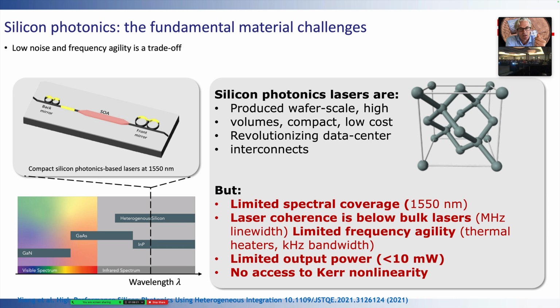material. And chief among them is the limited bandgap of 1 electron volt that prohibits making devices that operate in the visible. It has moreover limited power handling capability, so typically tens of milliwatts. Due to the low band gap, it also doesn't allow to harness its nonlinearity because one suffers from two-photon absorption. And this may sound very non-intuitive, even using state-of-the-art global foundries processes, it's challenging to get waveguides with losses that are, say, less than a dB per centimeter. And those factors combined have made silicon a wonderful material for microelectronics, but it has not allowed to make lasers or amplifiers or combs based on silicon photonics.